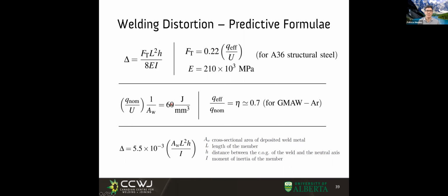We also said something that is especially interesting. If you remember when we talked about mass conservation, if we started with the cathode fall voltage and the anode fall voltage, and combined that with the deposition rate, we could calculate a relationship between how much material was deposited and the heat input. So here we have a relationship between the cross section of a weld and the heat input. And this is the exact number we used, which came from our values of voltage for the electrodes, and was 60 joules per cubic millimeter, right? That's what you're going to find in the mass conservation unit.